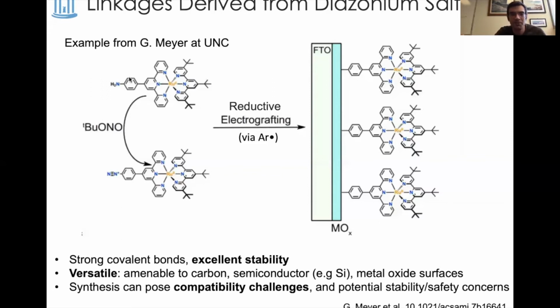And the general approach is that you undergo some oxidation reaction, usually of an amine in your backbone to make a diazo group. And then the diazonium undergoes an electrochemical reduction to generate an aryl radical, in this case, that then forms a bond to the metal oxide surface. So they tend to form pretty strong covalent bonds and have quite good stability. And this versatility in the surface chemistry is good.